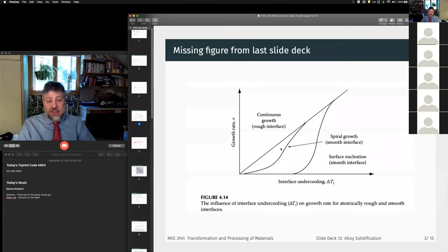So in the previous slide, I had mentioned that spiral growth and surface nucleation were slower, but I forgot to throw this picture in, right? And this just shows the growth rate as a function of the undercooling, and that at large enough undercoolings, they all asymptotically converge to the continuous growth rate for a diffuse interface.